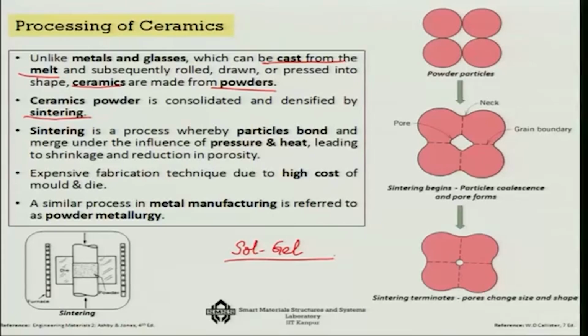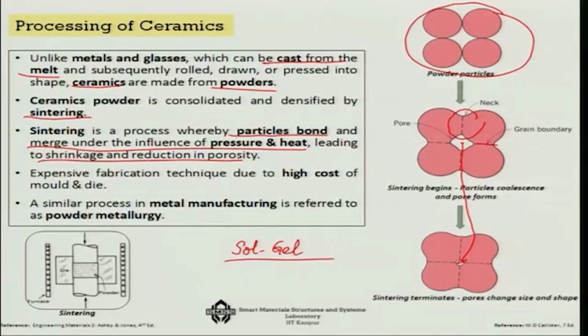So, ceramic powder is consolidated and densified by sintering. Now, what is sintering? This is a process whereby particles bond and merge under the influence of pressure and heat. High pressure and high temperature lead to shrinkage and a reduction in porosity as well. What we have tried to show here is that these are the powder particles to begin with, and then you apply high temperature and pressure, and there will be some pores and the particles are going to merge. These are the neck areas and the grain boundaries are here. As you apply more and more pressure and temperature, it shrinks from this to this. You can see that there are pores, but it is gradually shrinking.